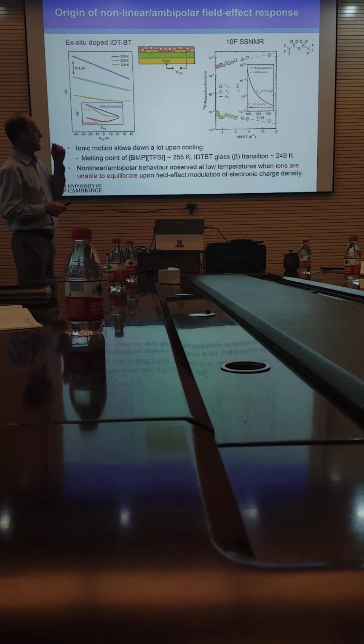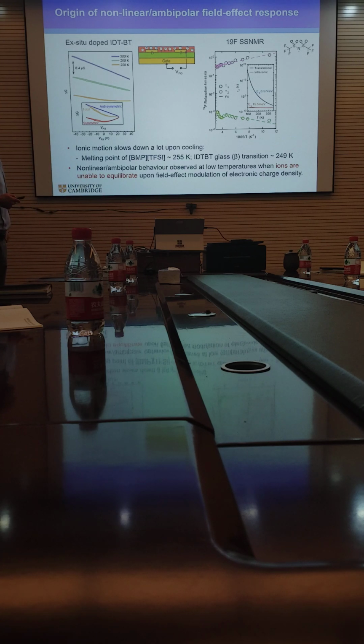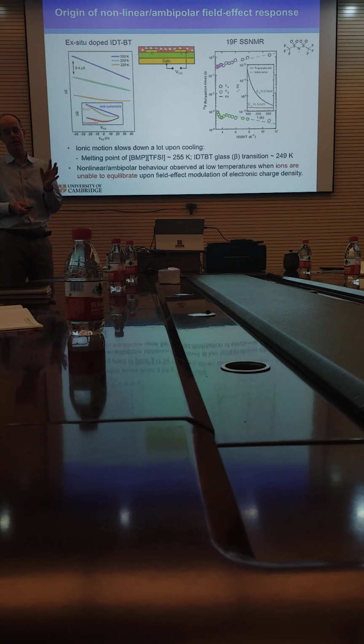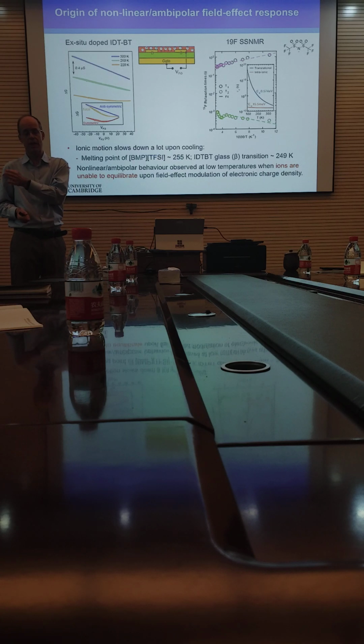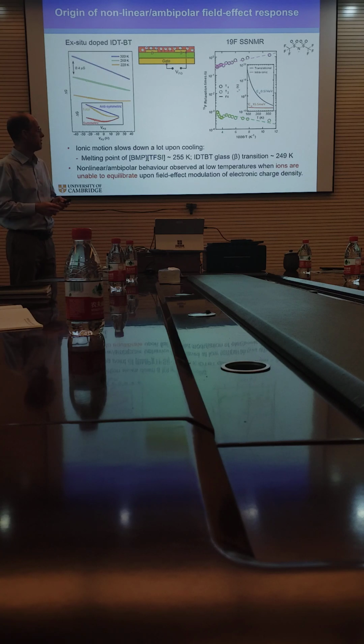And so we did some fluorine NMR. I don't have time to discuss it in detail, but in fluorine NMR you can basically look at the dynamics of the counterion. The counterion has fluorines, and you can look at how the dynamics of those fluorine counterions changes as a function of temperature. And what we saw is that at around 240 Kelvin, there is a particular motion, basically the dopant counterions stop moving. So they're unable to respond anymore and unable to move in the polymer